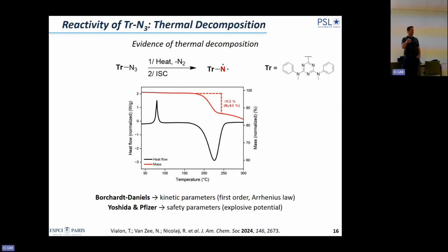And if you look at the DSC, we see that we have an endothermic peak here, which is the melting of the molecule, which is crystalline, so below 100 degrees Celsius, and a very highly exothermic peak here, which is the decomposition of the molecule.